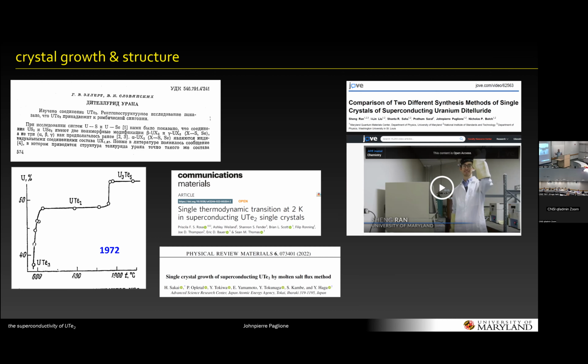So the stoichiometry or some kind of vacancy effect, I'm sure, is playing a role. But it's not discernible in standard X-ray experiments. It's at the sort of percent level. But you can do single crystal X-ray and that should detect it. It doesn't even see any sub 1% difference, no? Yes, as far as anyone has measured, there's no systematic difference. Then it must be much less than that. Yeah, that's what I'm saying. At the level of a percent, there's nothing that we can see. What about triple R?